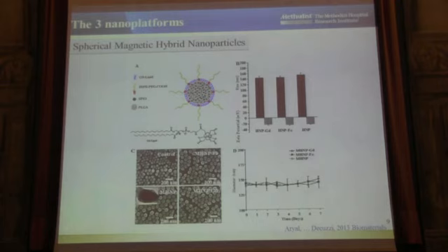So very conventional. The only thing that is changing is somehow the different compartments and the size, again, within 150, 200 nanometers, depending on the payload. Here we are putting inside ultra small superparamagnetic iron oxide. You can decorate the surfaces in this configuration with gadolinium so that you can do T1, T2 MRI imaging. You can do a number of things.